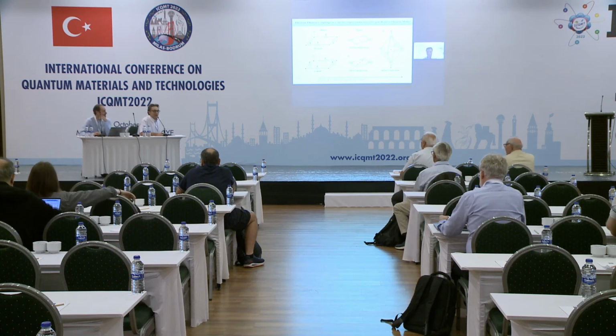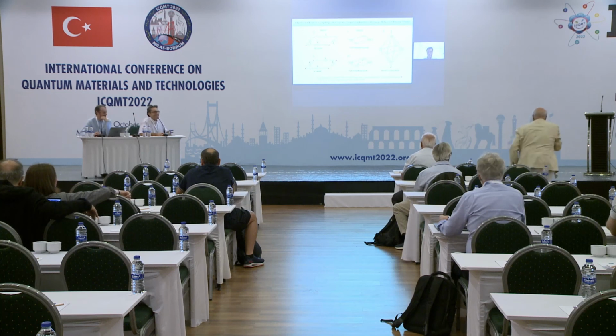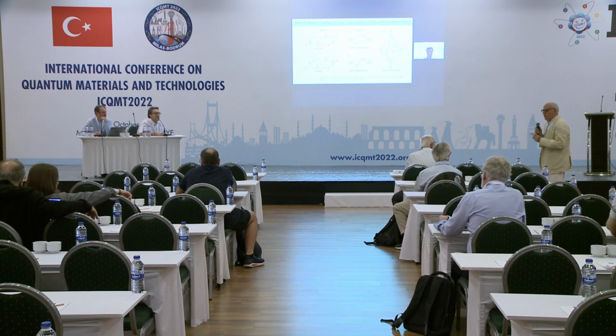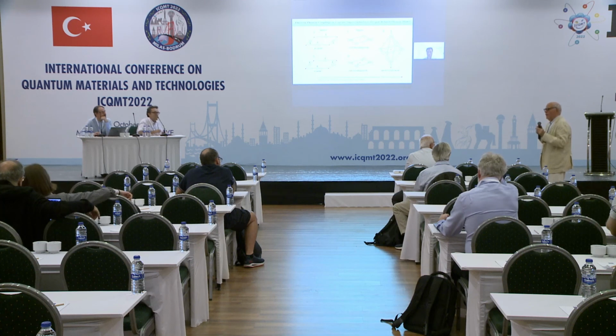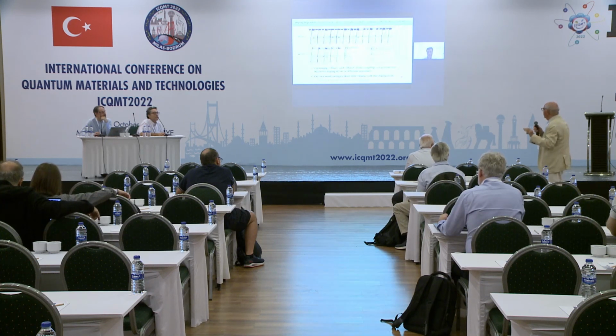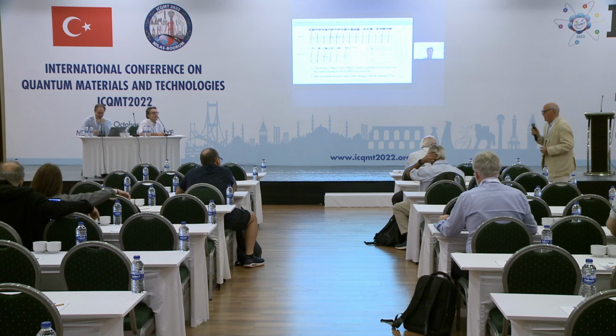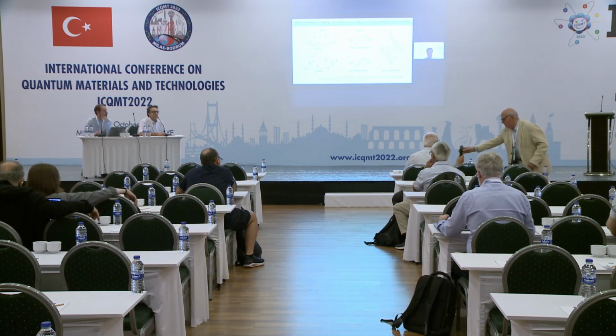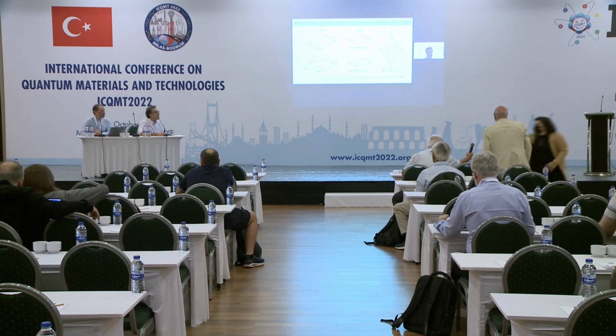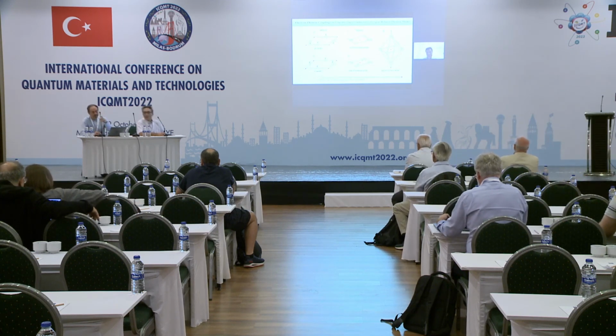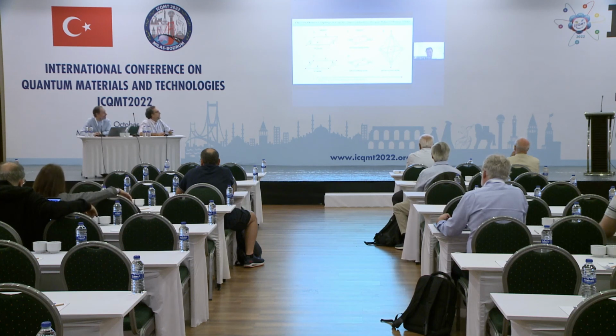Okay. Yeah. I think that the ARPES that Zhou presented is very important for quantum mechanics because it has very high energy resolution. And the new quantum mechanics is always in the range of 10, 50, 100 millielectronvolts. And this is new physics. It's not solid state physics. So that's why this high resolution result from ARPES is so important. You're right. The physical properties are determined by only a few millivolts or tens of millivolts near the Fermi level. That's why we are pursuing higher and higher energy resolution, because we are really probing very low energy electron states at the Fermi level.